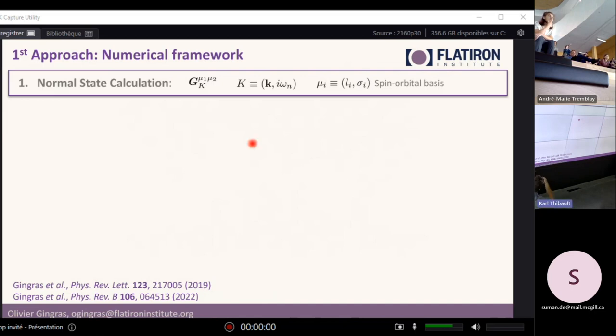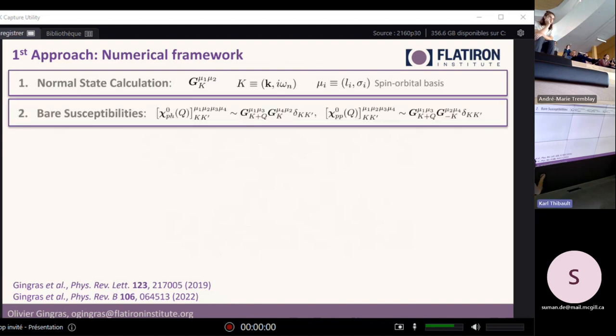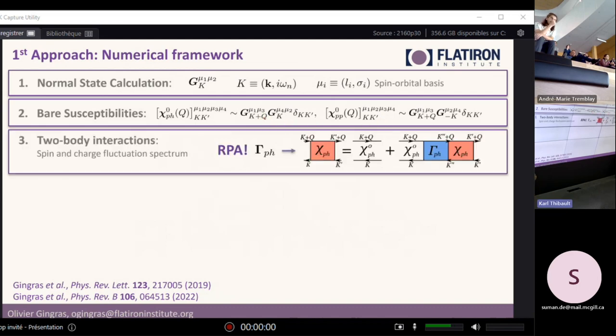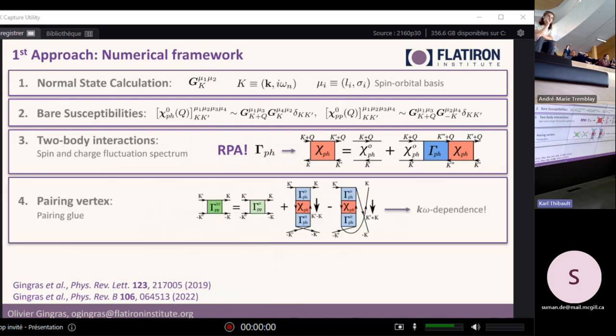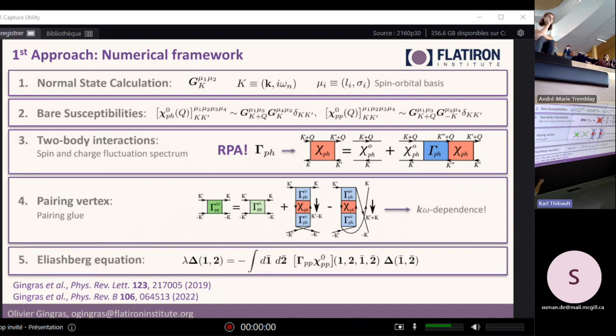First of all, we do a normal state calculation with DFT plus DMFT, or just DFT, or anything that you like that gives you a good one-particle propagator expressed in a specific basis, here in spin orbitals, so these t2g orbitals. With this, we can easily construct these bare susceptibilities, which are just the propagation of two electrons or two holes. And now we assume a specific particle-hole vertex, which will allow us to construct the whole spin and charge fluctuation spectrums, which are used as a pairing glue in superconductivity. And then once we have this operator, the pairing glue, we can solve the Eliashberg equation and look at the leading eigenvalues and eigenvectors.